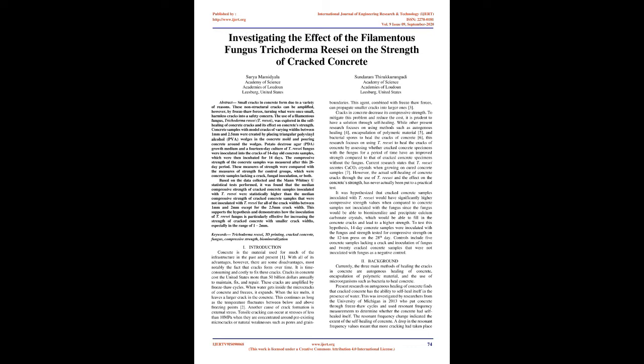This was especially true for the smaller crack widths of 1 mm, 1.5 mm, and 2 mm because the difference in the mean compressive strength for these crack widths for samples inoculated with fungus and samples lacking fungus was 140 psi, 350 psi, and 310 psi respectively. This supports the hypothesis and demonstrates how the inoculation of T. reesei fungus is particularly effective for increasing the strength of cracked concrete with smaller crack widths, especially in the range of 1 to 2 mm.